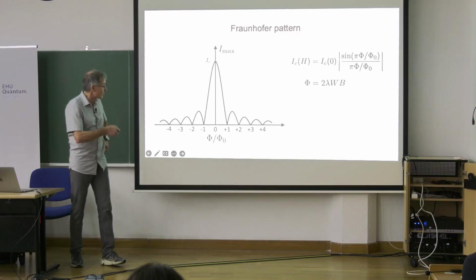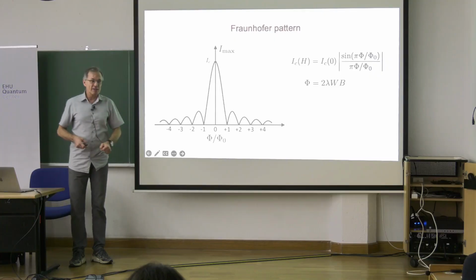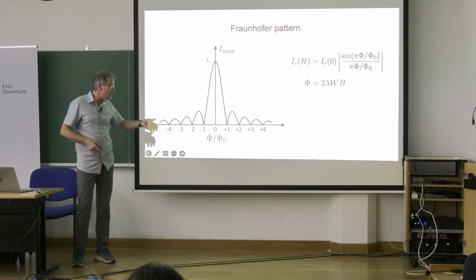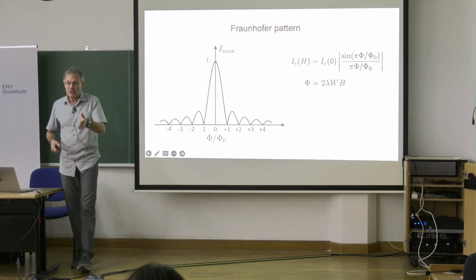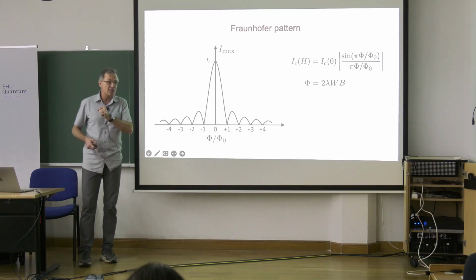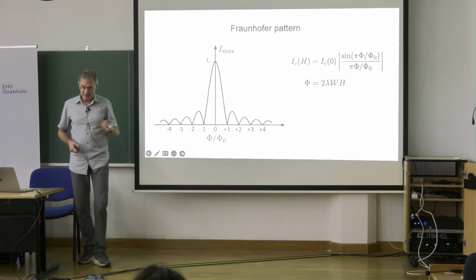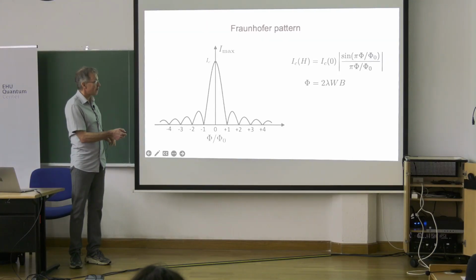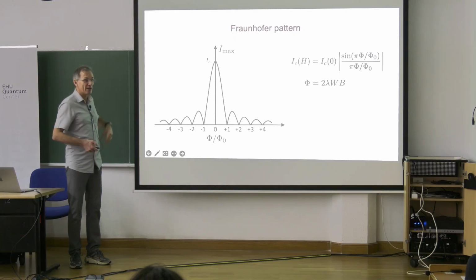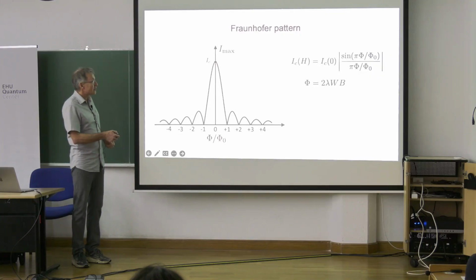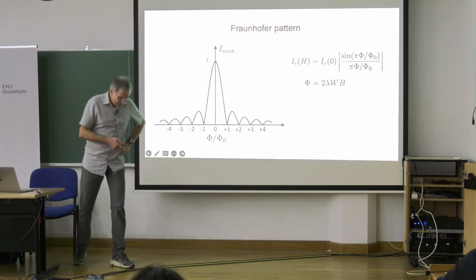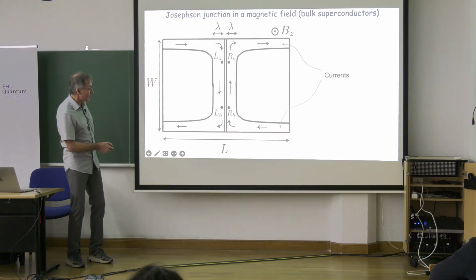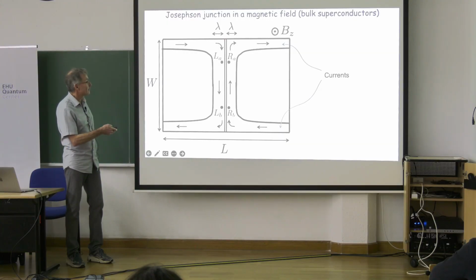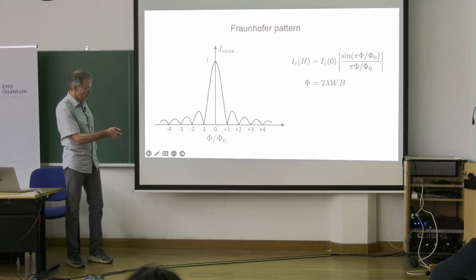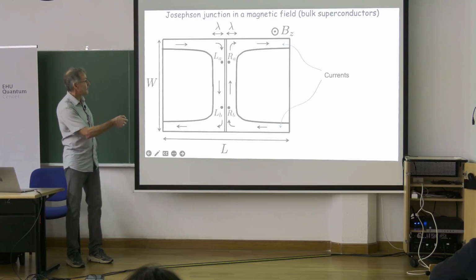It's called the Fraunhofer pattern, not because Fraunhofer discovered it in the Josephson junction, but because it is given by the same formula as Fraunhofer diffraction, which you study in optics. If you take a single slit and look at the electric field on the screen away from the slit, the amplitude of the electric field is sine of angle divided by angle. That's Fraunhofer diffraction. Here we have the same functional dependence, but for a completely different thing. This is for a bulk superconductor where magnetic field is expelled from inside, and the flux in this formula is the flux in the junction.